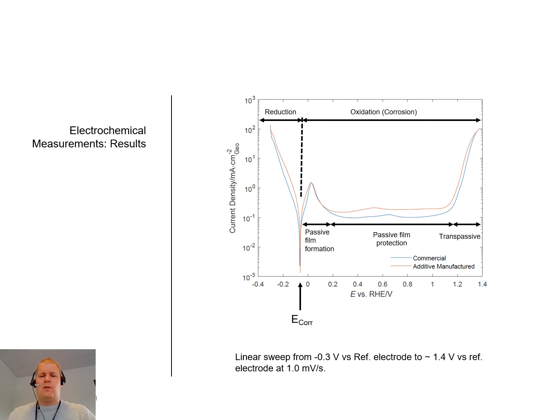Another experiment we conducted was so-called linear sweep voltammetry, where we changed the potential at a constant rate of 1 millivolt per second, starting at a value of minus 0.3 volt versus the reference electrode, going all the way to a value of roughly 1.4 volt. As you can see here, there's a dip in the plot indicating where the corrosion potential is. To the left of the corrosion potential, you have a reduction reaction on the sample, which can be everything from metal deposition to oxygen reduction reaction. To the right here, you have oxidation or corrosion of the sample primarily.